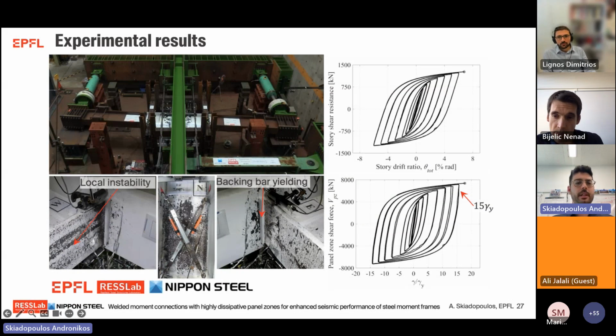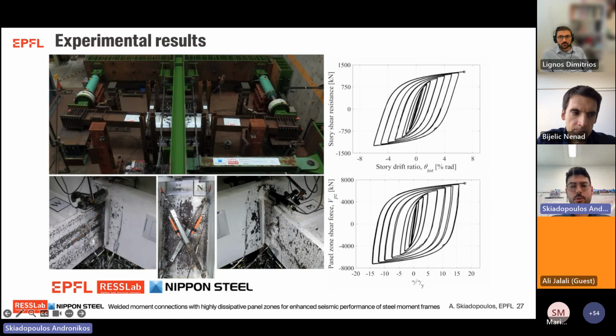Here we see that at 6%, there is some mild local instability in the beams, and there was some trace of backing bar yielding without any crack initiation or propagation in that region. And also, at this drift level, we reached the targeted panel zone shear distortions of 15 times the panel zone shear distortion at yield.